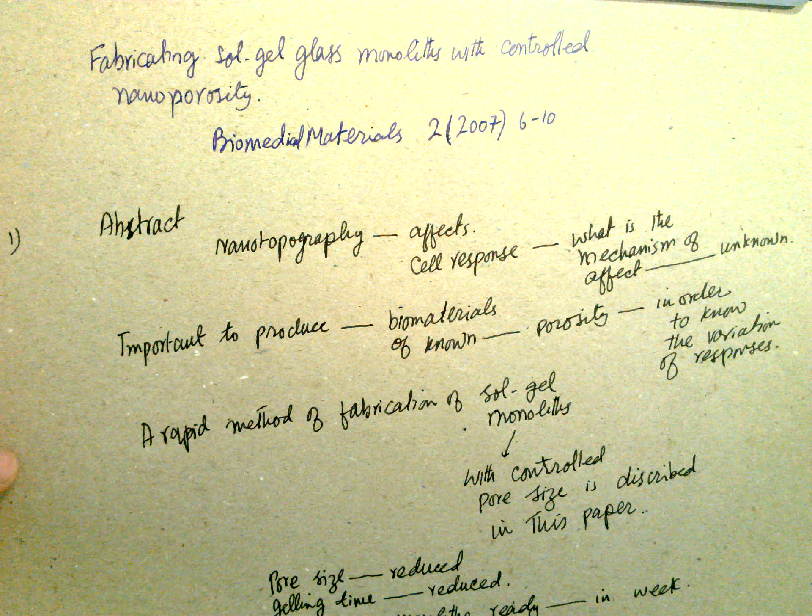Therefore uniform monolith discs should be prepared to investigate the cell responses to their nanoporosity. It is difficult because of their crack. It is difficult to get crack-free monoliths. Fabrication is difficult, it takes longer time because of the capillary action pressure caused by the water and alcohol interaction with the surface. Pore distribution is broad.